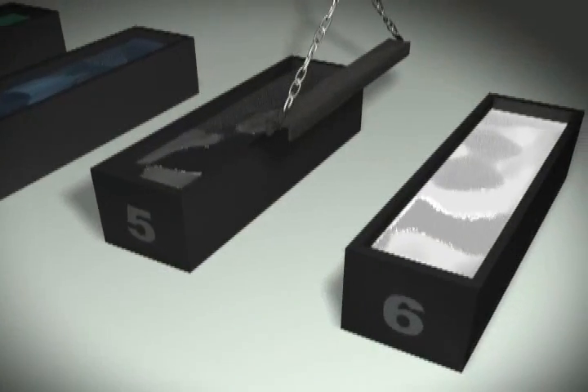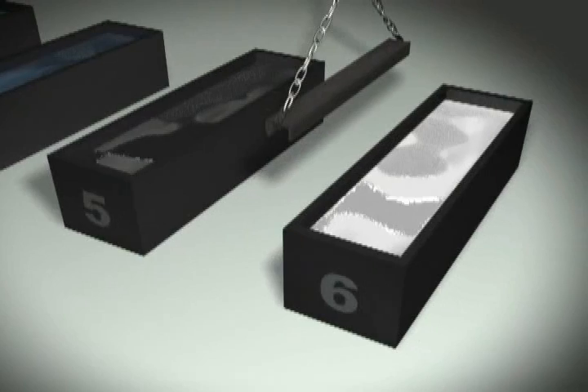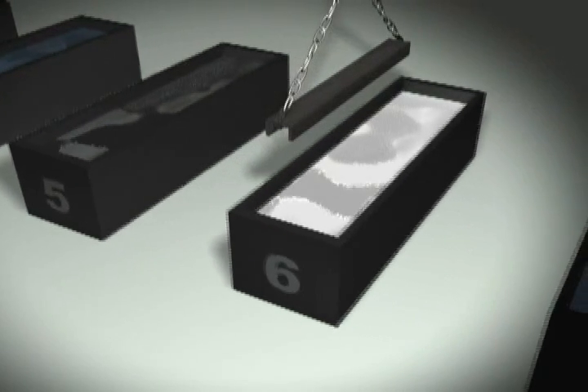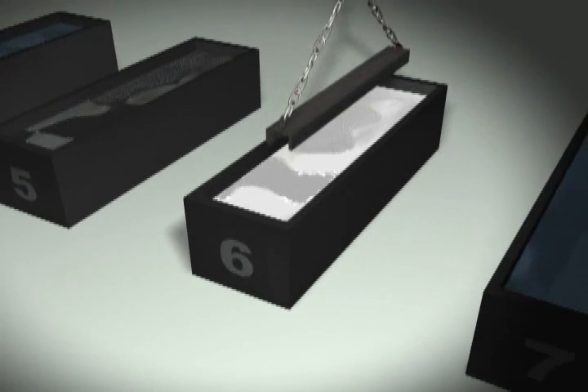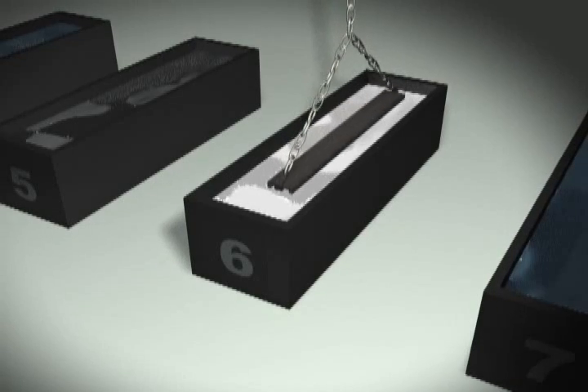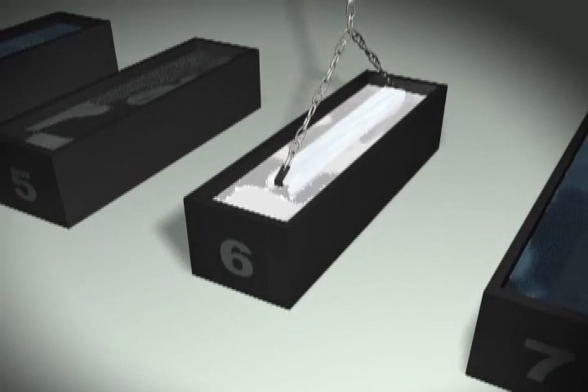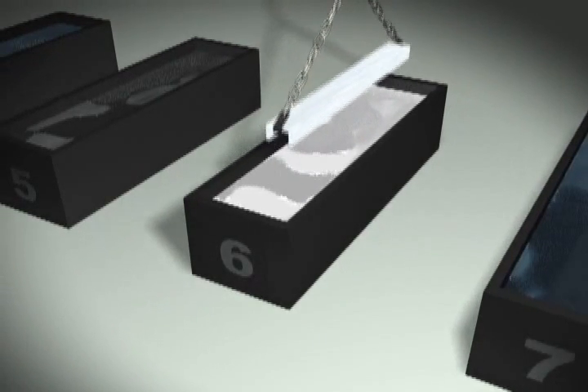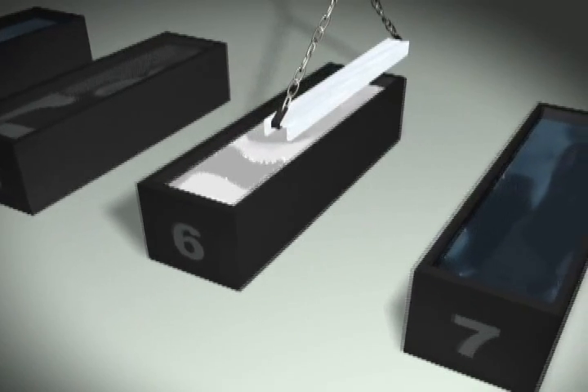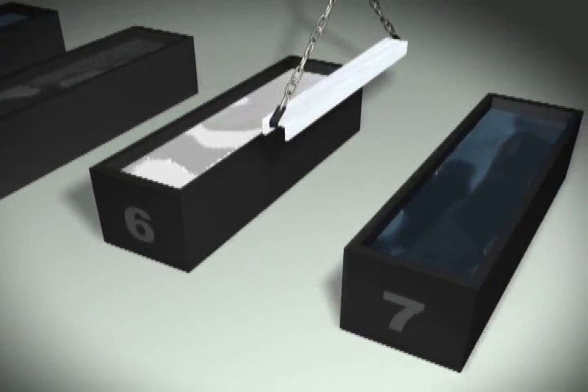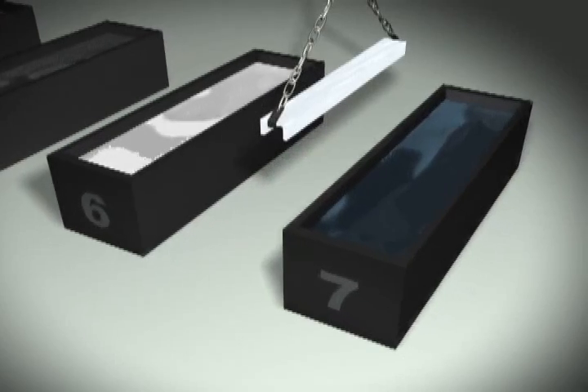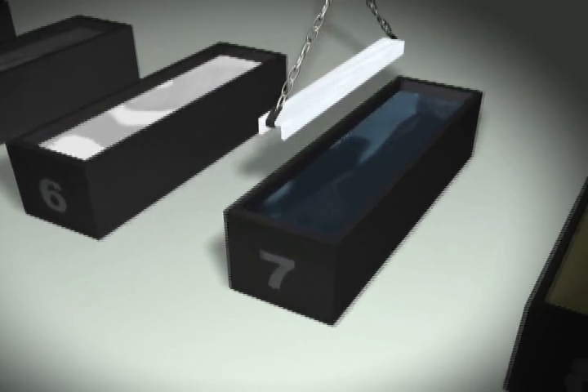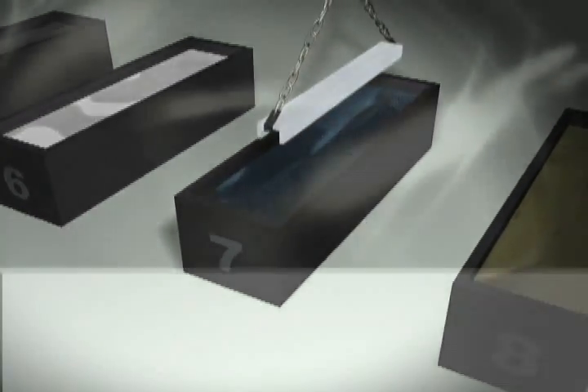Galvanizing. When the part is immersed in a zinc bath at the temperature of 860 degrees Fahrenheit or 460 degrees Celsius, the base metal of the material reacts with the zinc, forming iron-zinc compound layers that present specific characteristics, such as elevated hardness, offering resistance against abrasion and corrosion provided by the galvanizing.